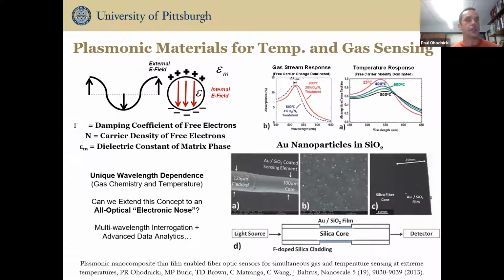We've also looked at doing things like incorporating plasmonic materials for temperature and gas sensing. In this case, what you're doing is you're embedding a nanoparticle in a matrix. This nanoparticle has a characteristic optical feature associated with it called a localized surface plasmon resonance. That feature depends on temperature. It also depends on the carrier concentration of the electrons in the particle, and that is related to gas phase chemistry. So by using a relatively simple type of a material, we can interrogate different wavelengths because of the difference in the gas phase and the temperature response.